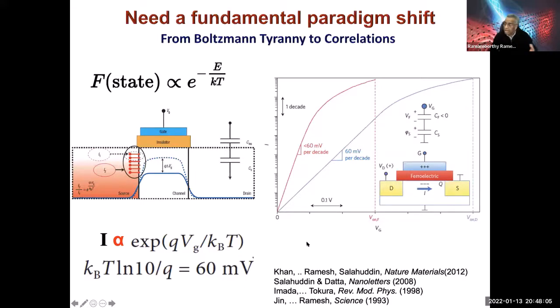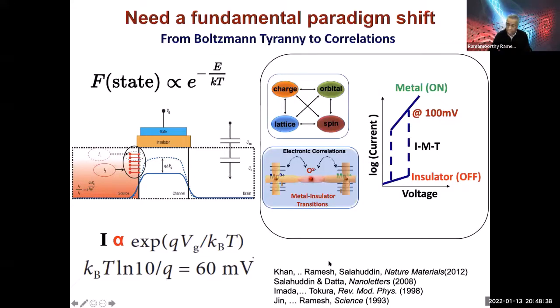Now, what Saif was saying is, if I put a ferroelectric gate in the channel or along with the insulator, I could create, temporarily, negative capacitance, and therefore I could reduce the slope. And indeed, this is actually from a figure that the person who reviewed our Nature Materials paper wrote. So in principle, you could go down to below 60 millivolts, maybe about 50 millivolts per decade by using this ferroelectric. So there's a lot of effort looking at hafnium zirconium oxide or other ferroelectrics, for example, to get the negative capacitance.